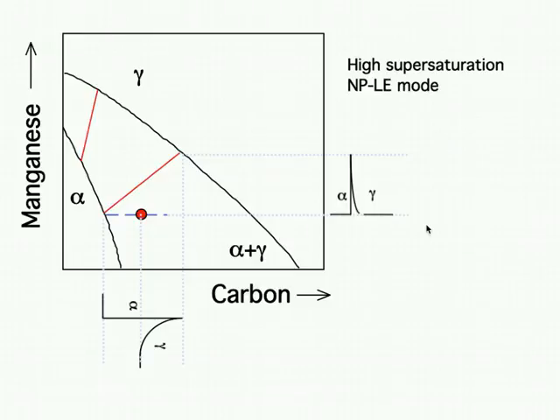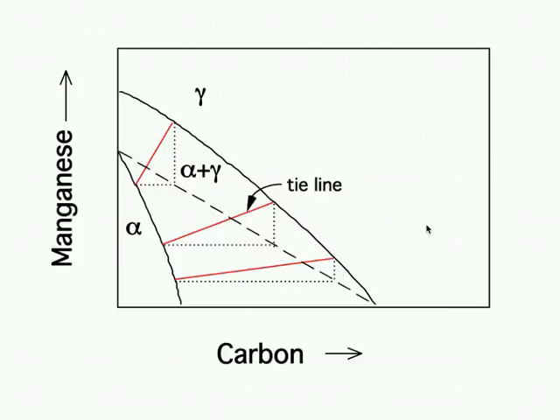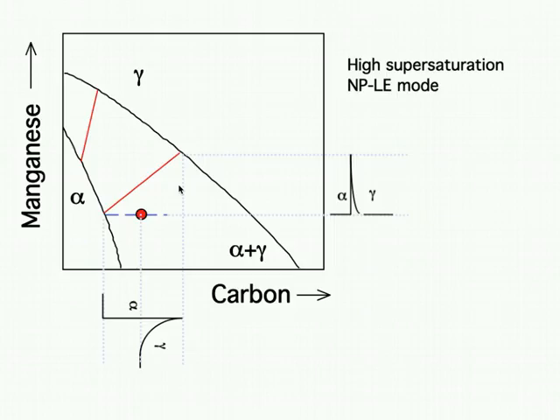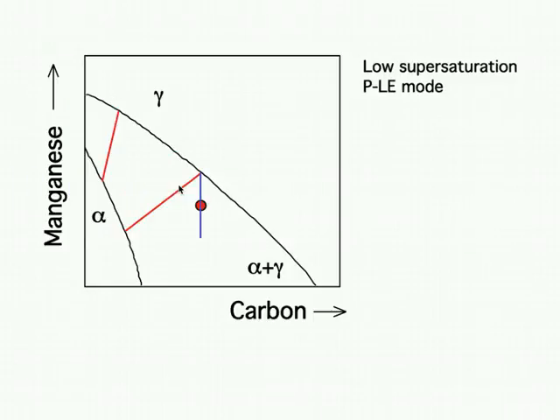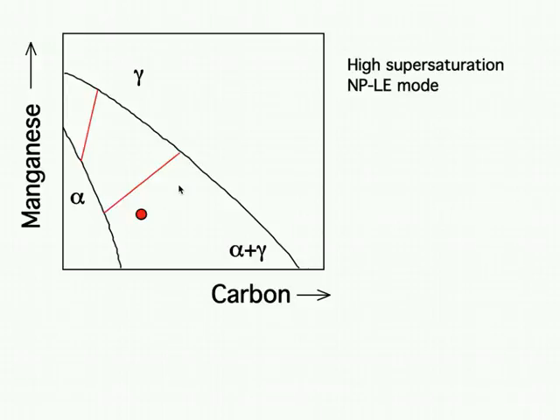How does the steel know which growth mechanism should operate under a driving force? Well, if we take our tie lines and we divide them into right-handed triangles. So let's see how we can pick a tie line which allows the manganese concentration of the ferrite to be similar to that of the alloy, so that there is negligible partitioning of manganese, and yet we are able to maintain local equilibrium at the interface.